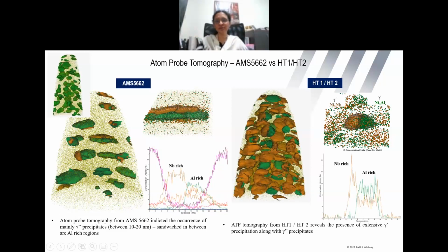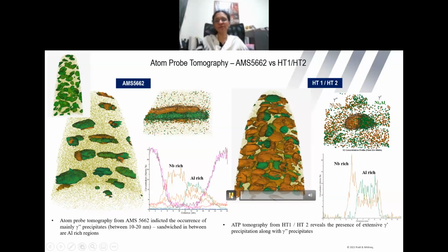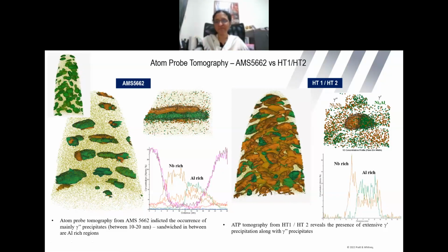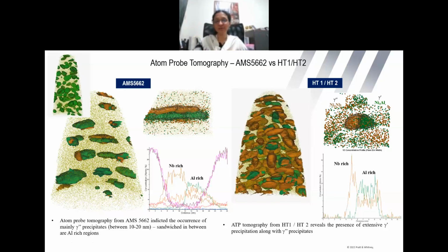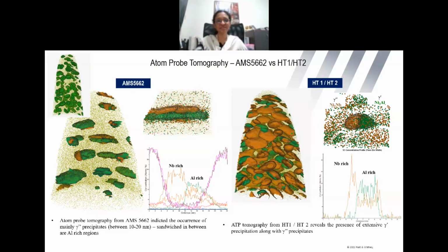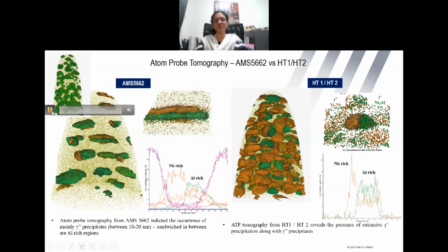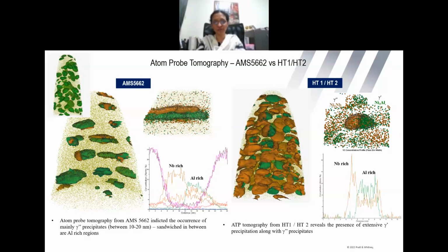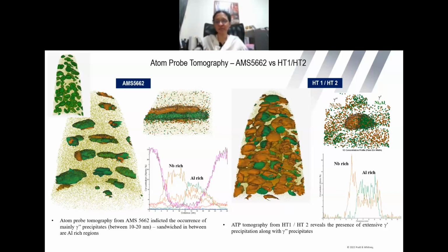So we compared these two with two different heat treatments. I think this works. I won't go into the details, but I wanted to show the students especially what kind of things that you can help us with. Most of the universities, especially a university like yours and IITs and NITs, are equipped with very high-end advanced characterization techniques. So we used atom probe tomography to actually decipher what was the root cause. And we were able to propose a heat treatment to Pratt & Whitney with a much superior notch sensitivity on par with the wrought alloy. So additive still has those challenges. That's what I wanted to show.